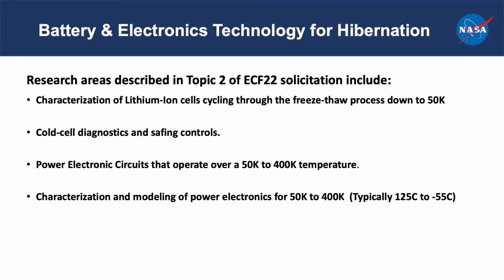On the electronic side, we're looking for circuits that can operate between 50 and 400 K, which is polar to equatorial temperatures. Ideally, circuits are composed of devices that are insensitive to temperature. We know that is not practical. You can use devices with flat response at temperature like gallium nitride, but not everything is made from gallium nitride. So we have to develop temperature compensation techniques to make sure all the devices cover the range of 50 to 400 K for the entire circuit.